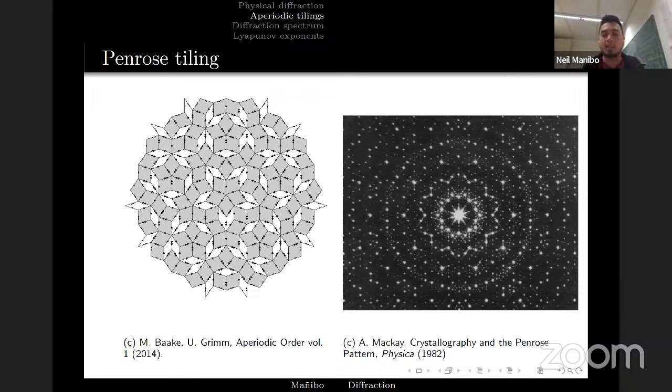And his colleague, who was, I think, in Cardiff, used an actual optical interferometer to check that, and he got this picture from that specific solid derived from the Penrose tiling. So as you can see, this has bright spots similar to the spots that Laue had obtained for the X-ray diffraction. The only difference is in this case, this is of course with lasers, so you really have bright spots now representing constructive interference. But the pattern of having bright spots is analogous to what they saw in 1912. So they thought it's not possible because only crystals can have a diffraction pattern like this.